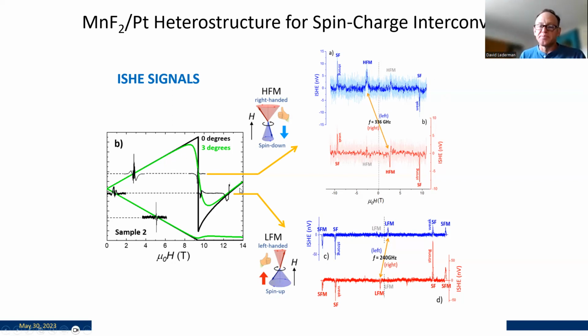but it was actually misoriented by about 3 degrees. We actually had to do this experiment several times because initially our samples were so misaligned that the sample would torque, because it's a bulk crystal. The fields are very big, and it would just come unglued and fall off the sample holder. So we don't have a way, in this case, to change the angle of the field.